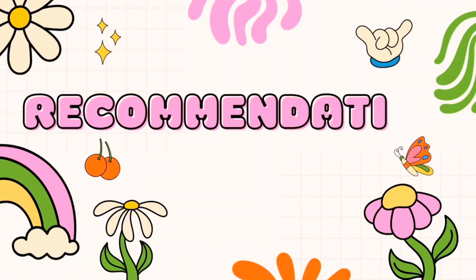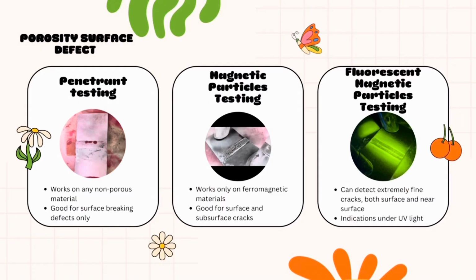This is the recommendation testing. After carrying out all the inspections, we discovered a porosity on the sample. Compared to penetrant testing and daylight magnetic inspections, fluorescent magnetic testing offers stronger contrast, better indication visibility, and the ability to detect both surface and near-surface defects in ferromagnetic materials.